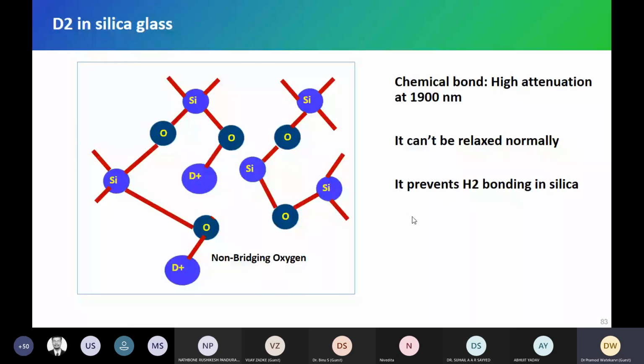So high attenuation at 1.9 micron, that I told you, deuterium makes it. So we can avoid OH attenuation in future by adding deuterium at the manufacturing of optical fibers. Once we manufacture optical fibers, we take it and put it in a chamber containing deuterium. Just 2% deuterium, that's all. Keep it for 18 hours at room temperature, and it's okay. It's good to go.